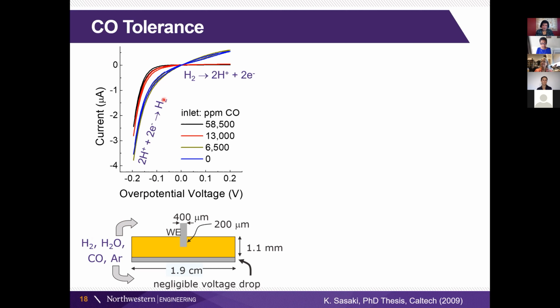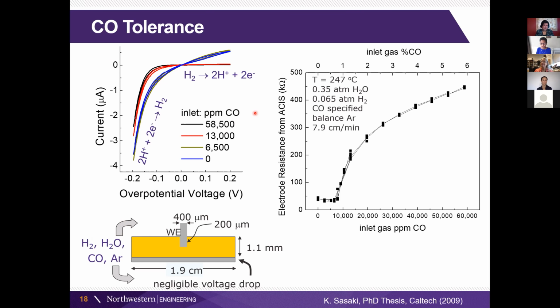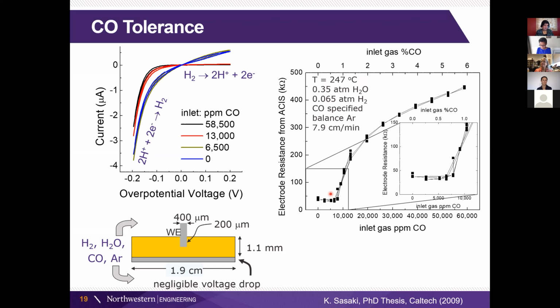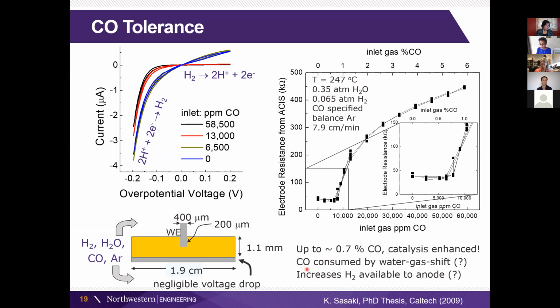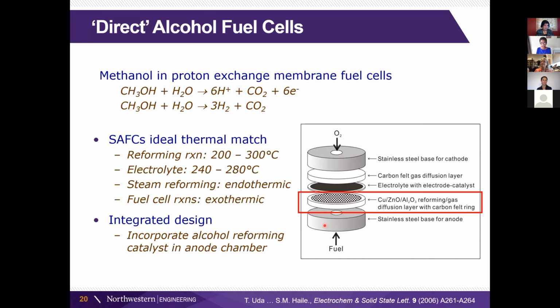And what you can see is that there's really very little impact on this polarization curve as we increase the amount of CO. And so the electrode resistance that we measure for this electrode, and again, I won't go through the details of how this measurement is done, but the key is that the resistance is stable with quite a high CO input in this region here. And it's only when we have very high amounts of CO that we start to get some electrochemical resistance at that interface. And so in fact, the CO is being consumed by the water gas shift reaction because we have a lot of water that's also coming in, and that is increasing the hydrogen that's available to the anode, and the CO is being converted to CO2. So that's great. And this is also what drove us to consider these direct alcohol fuel cells.